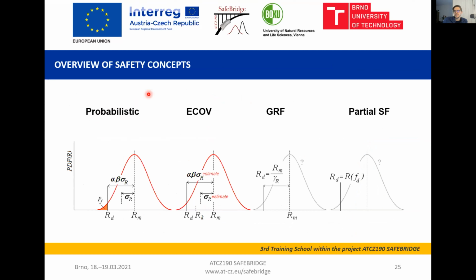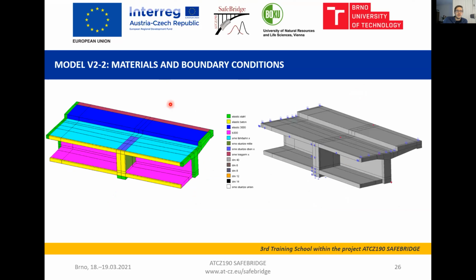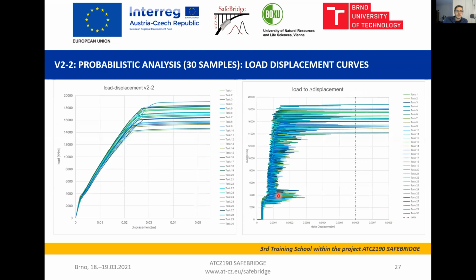The overview of safety concepts and safety formats we used for the assessment: we used the probabilistic assessment, the ECOV assessment, the global resistance factor, the partial safety factor, and also the global safety factor method. Here I'm going to show the results of the model V2. Here are the materials and the boundary conditions as shown in the first slide. We created 30 samples by Latin hypercube sampling with the SARA tool. Here you can see the 30 load displacement curves, and on the left-hand side and the right-hand side, the load to delta displacement curves. And this line here shows what we took as the point of failure and calculated the load.